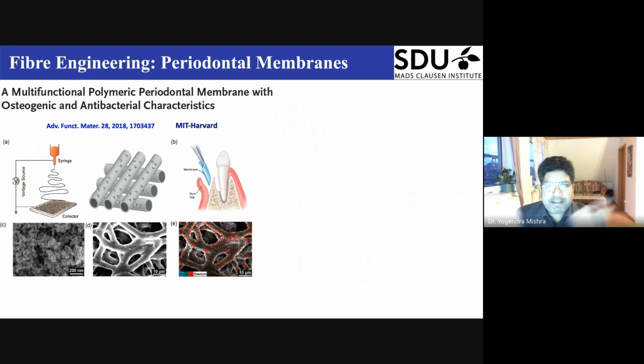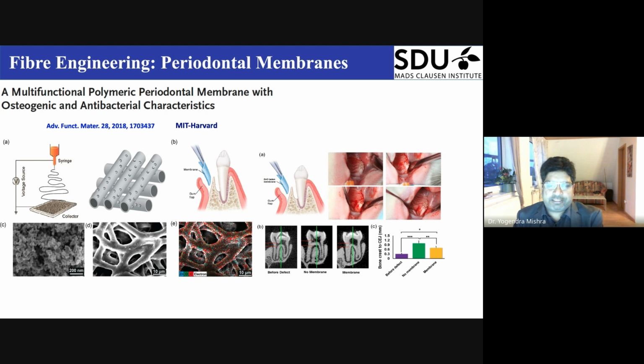But I'm mainly a materials engineer, and I always keep my focus on creating new materials. That's where, in collaboration with MIT, we started working together, to see if we can put these tetrapods into fibers by electrospinning. Initially, they hesitated, because they were breaking the tetrapods, and when they were putting them into the fibers, what happened? These fibers were used as a membrane to treat the root canal, and they nicely demonstrated, with 2% zinc oxide, the suppression of bacterial growth at the root canal.